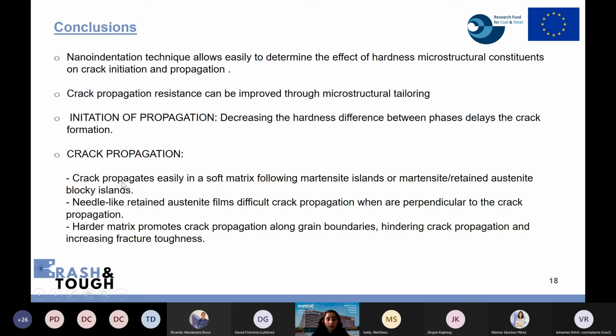About crack propagation, crack propagates easily in a soft matrix, following martensite islands and connecting them. Retained austenite films make crack propagation difficult when they are perpendicular to the crack propagation, and a harder matrix promotes crack propagation along grain boundaries, hindering crack propagation and increasing fracture toughness. So that's all.